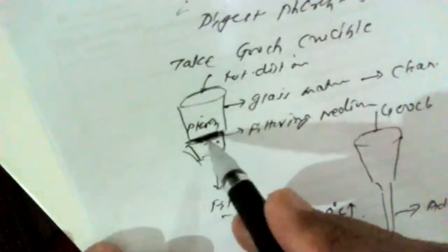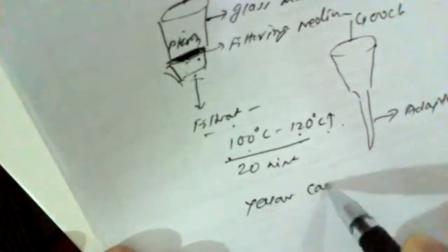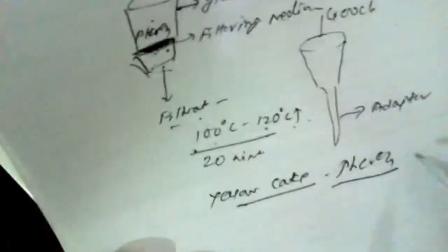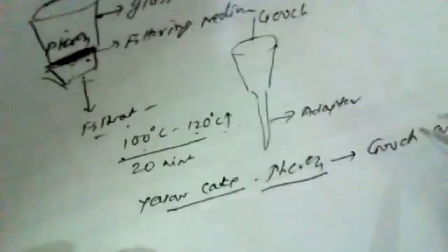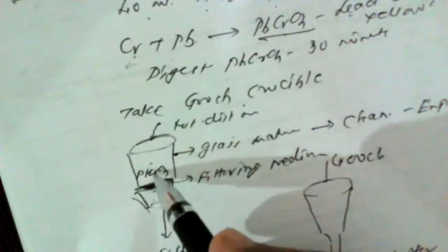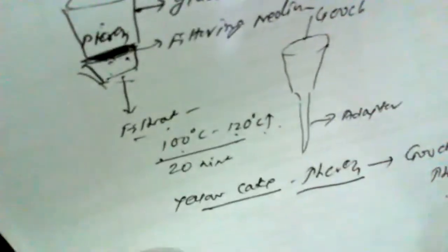After around 20 minutes, this precipitate is free from moisture and dry, and a yellow colored cake of lead chromate is obtained. We have to weigh this Gooch crucible along with the precipitate, because we weighed the crucible before the transfer of the precipitate. After transferring and drying the precipitate, we take the weight. So the weight of this Gooch crucible is higher than the previous, empty weight.